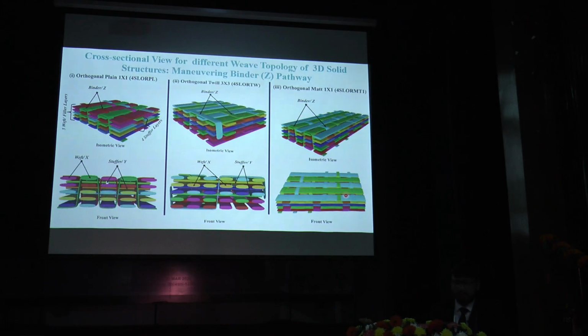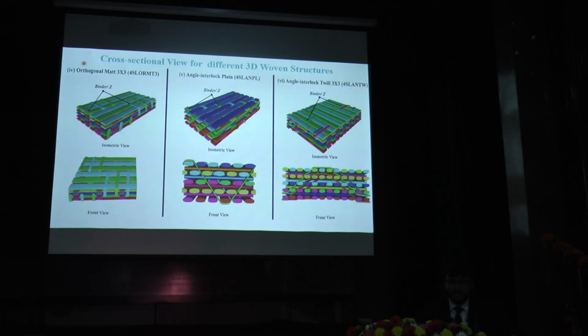Three of them here are very conventional plain structures where the crossover point is quite high. When we change the binder pathway, this is orthogonal twill, there's a basket structure with a shorter float. That's why I gave it the name mat 1 up, 1 down. When I increase the length of the binder pathway, mat 3 up, 3 down, and then we change the perpendicular direction of the Z reinforcement on the plane in a very slight angle. We call it angle interlock - conventional angle interlock plain, and then angle interlock twill.